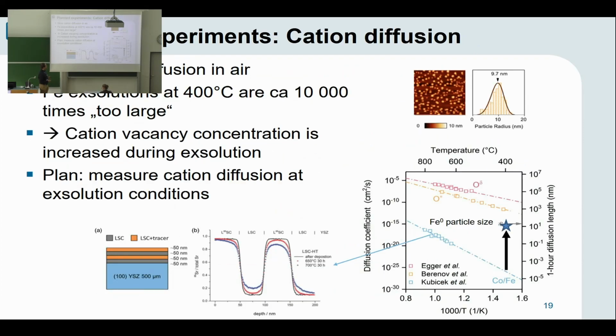Furthermore, we want to investigate why the exsolution and cation segregation processes are so fast. Because actually, from bulk diffusion experiments that were carried out in ambient air on thin film multilayers of perovskite thin films, A and B side cation diffusion coefficients were determined by Kubicek. And what he found is that at relatively low temperatures, below 600 degrees, the diffusion coefficient is very slow. And actually, all cations should remain on their lattice sites.